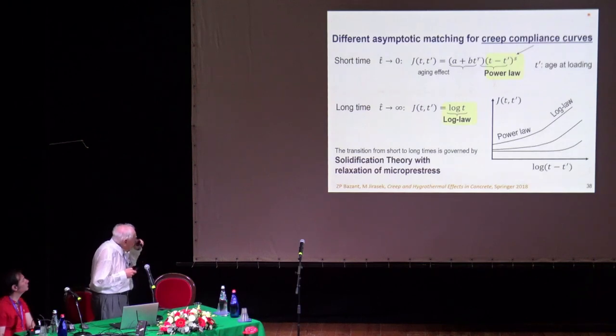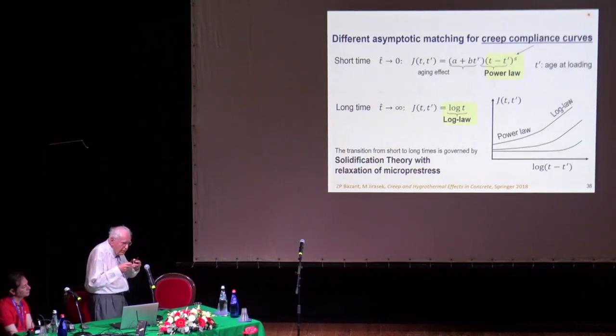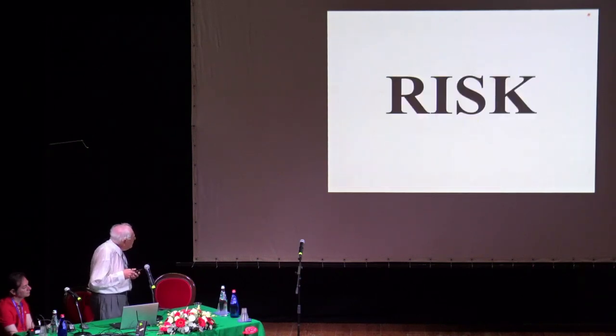Now, another interesting point is the creep compliance curve. You have a power law for a short time because it's self-similar. That goes to a power law for the rate. So it goes to a log law, exponent zero. And then you have a logarithmic law. And then you have the aging effect, which needs to be explained through hydration. And this is part of, I will not go into detail, solidification theory, and also relaxation of microprestress generated in the nanostructure by mismatch of expansions.